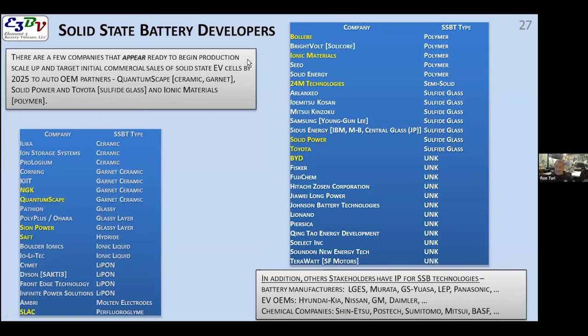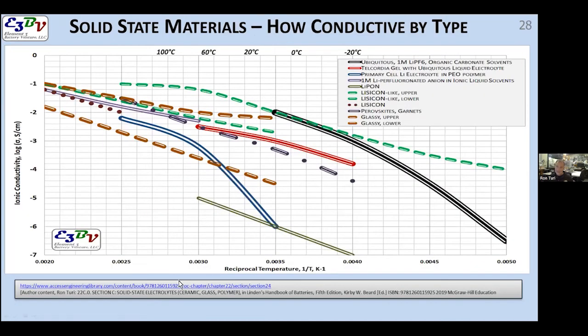Well, there are many different approaches here on solid state. There's no way we can cover everything that's here, but they generally fall in 3 buckets: ceramic style, like QuantumScape; sulfides of different kinds, like Solid Power, and many others. Actually, it's probably the most popular kind; and polymer type, like Ionic Materials. When you look at the ionic conductivity, this is probably the part of solid states that's best developed, finding something that will conduct lithium ions well enough. And usually these things are done by using Arrhenius graphs like these to assess the activation energy of the ionic transport, because it's all about mobility. In liquid-based systems, you would relate mobility to viscosity of the liquid that's the ion carrier. But here, you're relating it more to a diffusion-based mechanism. And even though, in principle, and proven 100 whatever years ago, that they're related, the truth is they do have 2 separate mechanisms, at least in ionic transport.